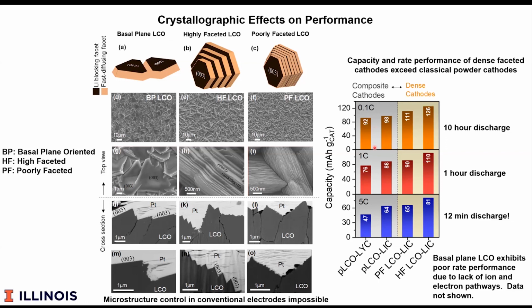What I think is significant is that even at these very high rates, this is now a 5C, so this is a 12-minute discharge or 12-minute charge. These operate symmetrically. The capacity of the dense cathode is about twice that of a composite cathode, and this really is fundamentally an effect of exposing the fast diffusing facets and limiting the tortuosity in the system.